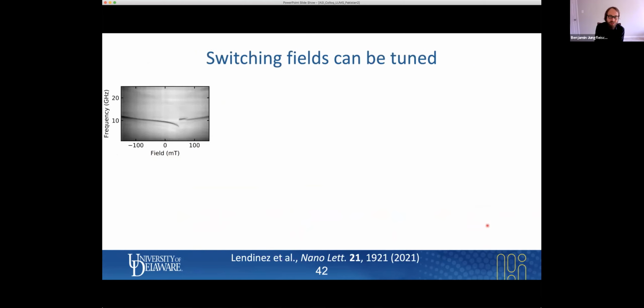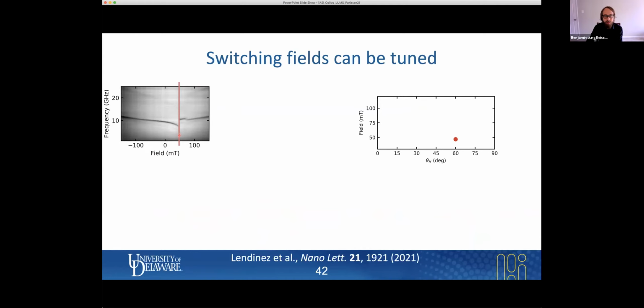And to show this tunability, I'm now going to show the switching field extracted from the experimental data as a function of the in-plane field angle. So I'm showing here 60 degrees. Red again is permalloy, blue is cobalt iron. I'm doing this now for all different in-plane field angles, and I get this map.